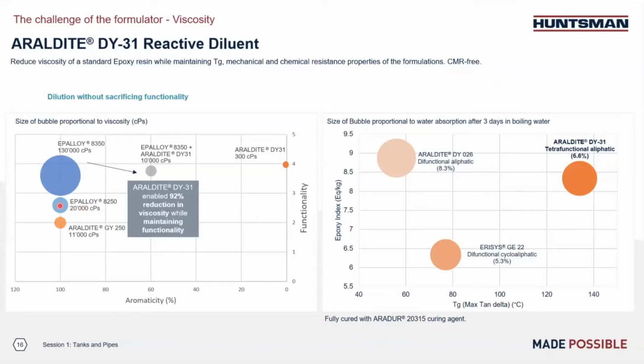But if we use a mixture, such as a mixture of 8350 with DY31, in a 60-40 mixed ratio, we can have a mixed viscosity of only about 10,000 centipoise. And this is even less than standard bis-A type epoxy resin viscosity at room temperature. So 10,000 centipoise compared with 130,000 centipoise basically means we reduce viscosity by 92%, right? But because DY31 has high functionality of 4, this mixture still has a high functionality of about 3.76. This demonstrates that by using those high performance reactive diluents, we can reduce the system viscosity without sacrificing the performance.